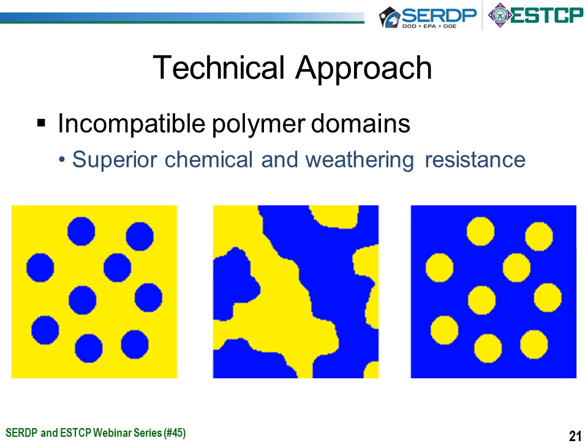And what we really did within the program is we used clear resin systems to screen what resin systems would be worthwhile pigmenting. So it was a sort of a fast throughput way to evaluate things. So we would try to obtain good chemical resistance and low gloss in clears. So we basically made clear resin systems, checked chemical resistance using methyl ethyl ketone, and if it touched the resin system, basically if it did any effect on it, by experience we knew that this would not make a coating system that would pass the requirements in the military specifications for chemical resistance.